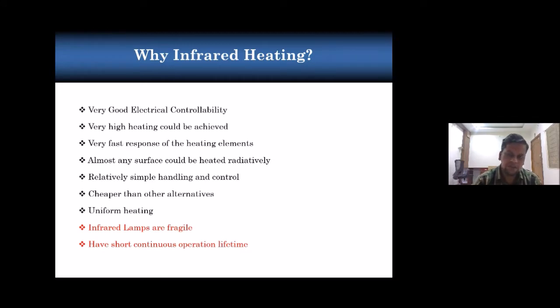Now the main problem with infrared heating is surface emissivity. We have to make the surface very close to a black body to simulate perfect infrared heating and absorption. Apart from this, it has some cons also. All these infrared lamps which are assembled on the heater are fragile in nature because these are quartz lamps. One more problem is short continuous operation. When we heat up to its peak rating, its life will come down. The life of the lamp at rated voltage will be around 10 minutes maximum.